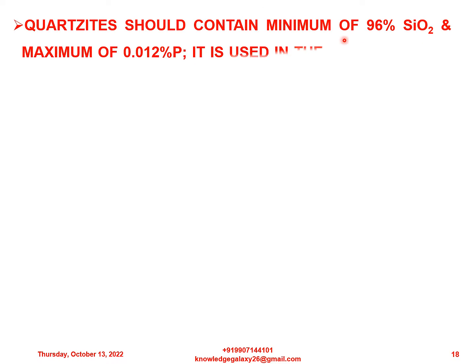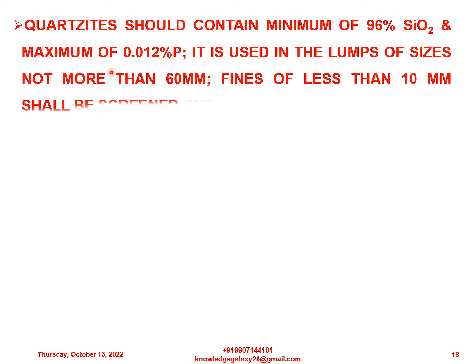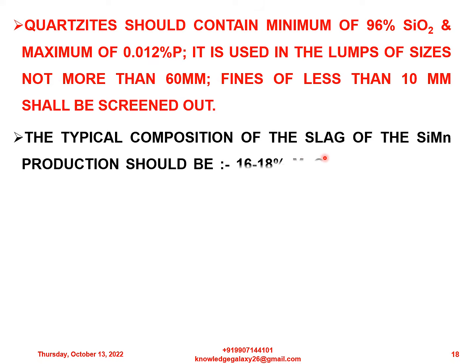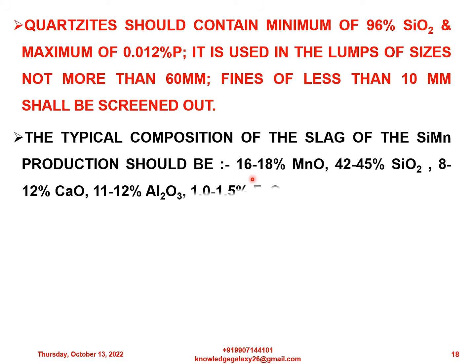Quartzites should contain a minimum of 96% SiO2 and a maximum of 0.012% phosphorus. It is used in lumps of sizes not more than 60 mm. Fines of less than 10 mm shall be screened out. The typical composition of the slag of the silicomanganese production should be 16 to 18% MnO, 42 to 45% SiO2, 8 to 12% CaO, 11 to 12% Al2O3, 1 to 1.5% FeO and up to 15% MgO. My dear friends, this is very critical information which I just shared with you all. So do remember this very carefully.